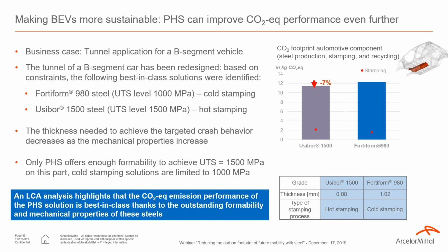We kept all these requirements, and we checked up to which mechanical properties we could make the part by considering both technologies, cold and hot stamping. Based on our results, this part would have been feasible in Fortiform 980 steel, so a UTS of approximately 1000 megapascal in cold stamping, and in Usibor 1500, a UTS level of 1500 megapascal. So for the same application, we could have 500 megapascal more in PHS steel. So we could, by the way, downgrade the thickness of the PHS part to keep the same mechanical performance.